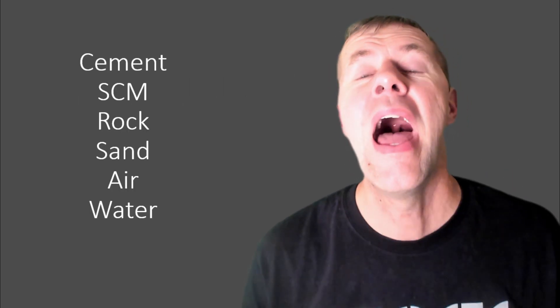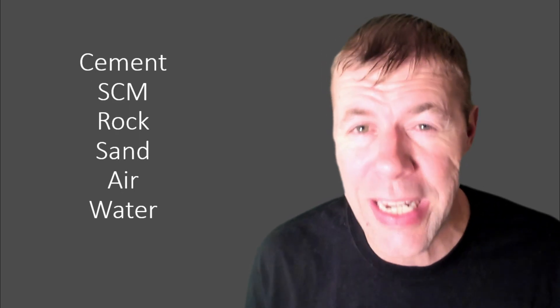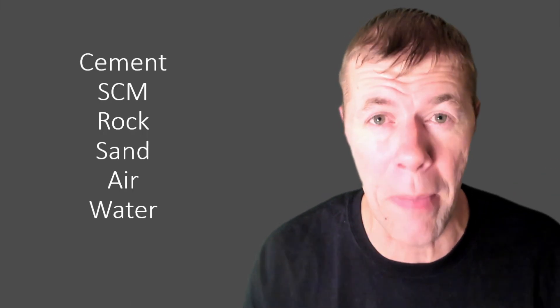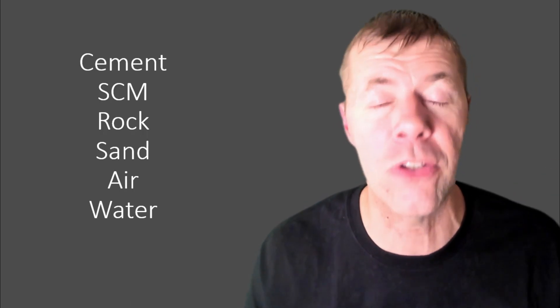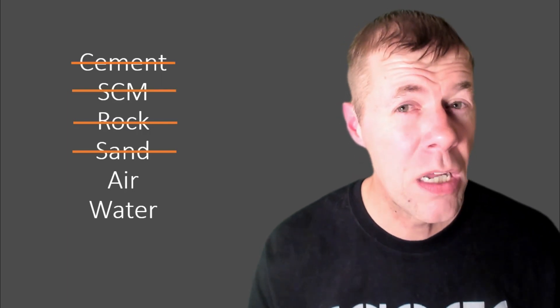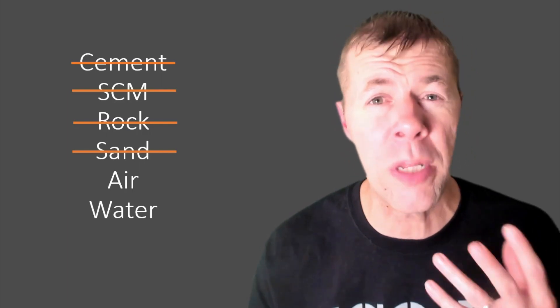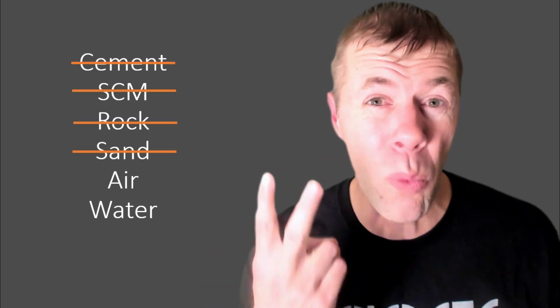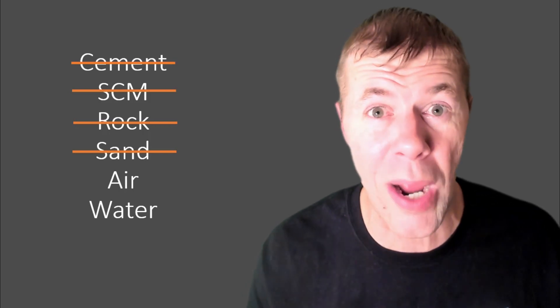what in the world in a concrete mixture impacts the strength of that concrete mixture? Well, I'm showing you on this slide, every single ingredient that's typically in a concrete mixture, and believe it or not, every single one of them has the ability to impact the strength of your concrete. However, if you look on a day-to-day basis, so let's say I gather up a given mix design, what changes on a day-to-day basis? Well, not the cement, not the SCM, not the rock, not the sand, all of those are pretty much fixed. There's some fine adjustments, but they're all pretty close. But the air content and the water content, that can change, and that can change drastically, and that can make it hard to predict what the strength is.